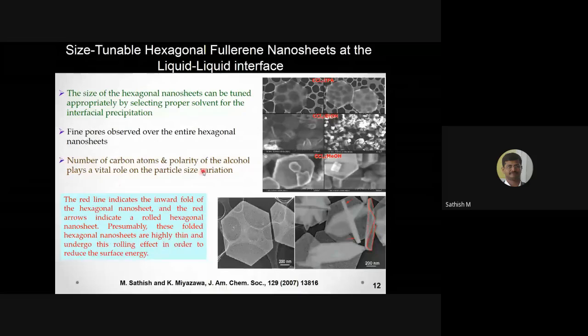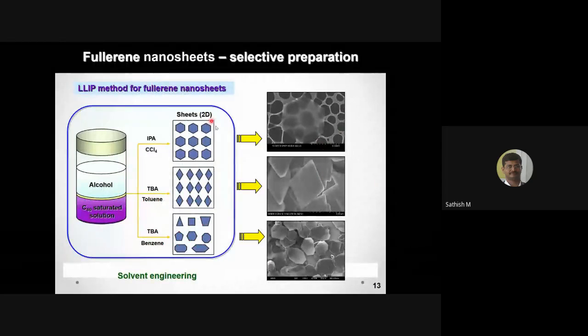So the number of carbon atoms and polarity of the alcohols play a major role in the particle size variation. So here we simply change the alcohol nature, and we were able to tune the size of the sheet, but still all these cases are sheets. Interestingly, in the same system, when I use carbon tetrachloride and isopropyl alcohol, I got a benzene-like structure. Okay, the sheets are formed, but all the sheets are benzene-like shapes. Okay, when I use a C60 saturated solution made up of toluene and tertiary butyl alcohol, that means instead of carbon tetrachloride I use toluene, and instead of isopropyl alcohol I use tertiary butyl alcohol, then I was able to get this kind of rhombohedral sheets.